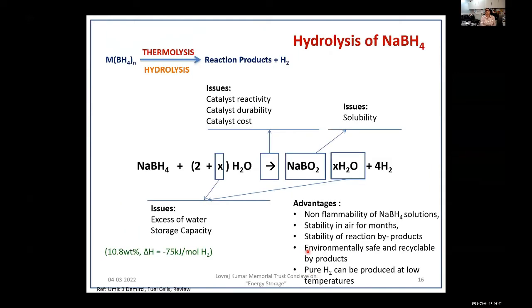Another class of materials which are known for their higher storage capacity is the various borohydrides. With these borohydrides, we can get hydrogen either by means of thermolysis, by heating them, or by putting them in water. When you use thermolysis, the temperatures are higher. So sometimes hydrolysis favors the reaction. You can do that at room temperature.